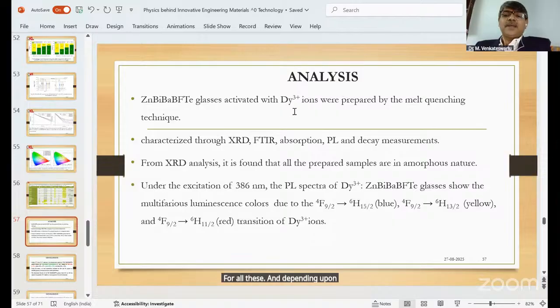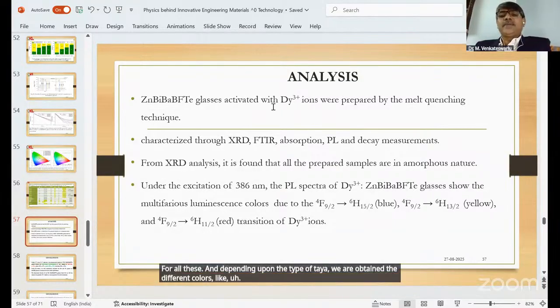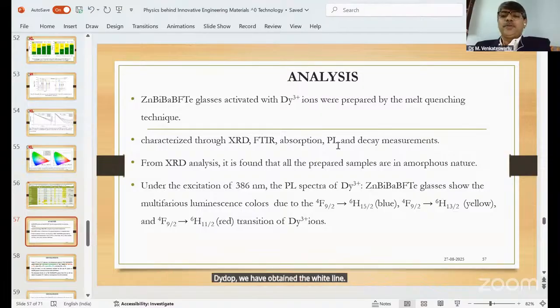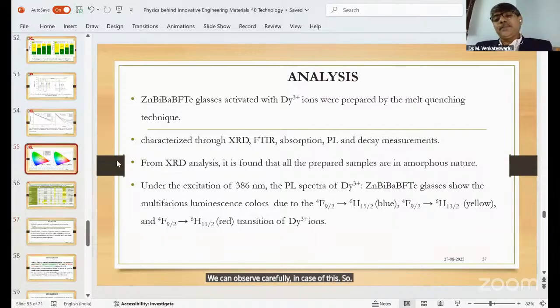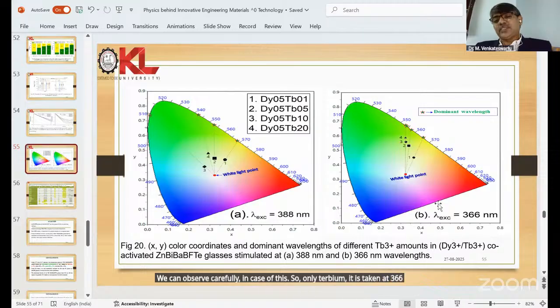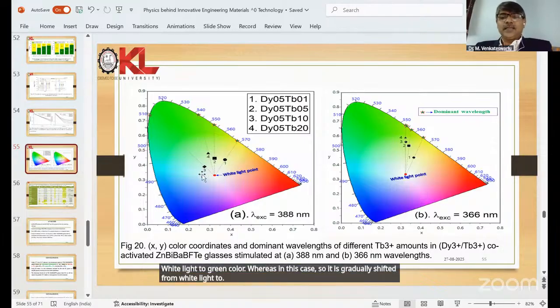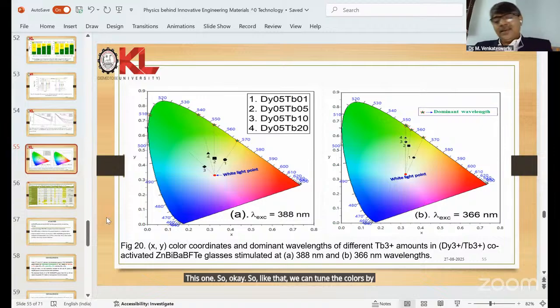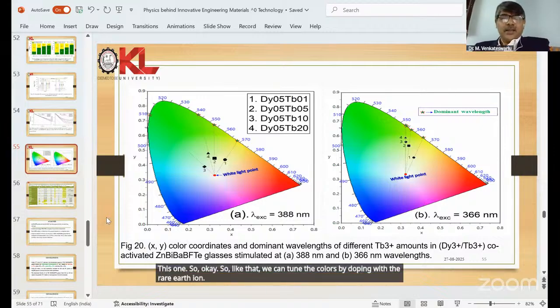And depending upon the type of the ion, we obtain different colors: Dy doped, we obtain the white light, and Tb doped, we obtain the green. By doping with the Dy and Tb combinations, it shifted from white light to green color, based on the concentrations as well as excitation wavelengths. We can observe carefully in this case, with only terbium taken at 366 nanometer excitation, it is shifted from white light to green color. Whereas in this case, it is gradually shifted from white light to this one. Like that, we can tune the colors by doping with rare earth ion concentration into the glasses.